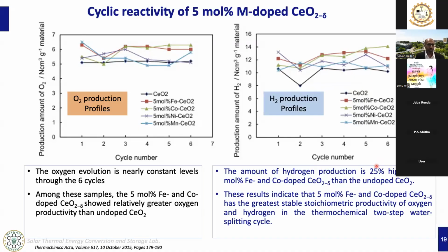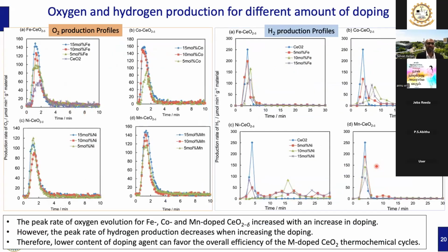This slide shows the overall oxygen and hydrogen production of all samples for different amounts of doping. This slide shows all samples, like 5 mole percentage of iron, 10 mole percentage of iron, 15 mole percentage of iron, and other materials also, from 5 to 15 mole percentage of doping. From all results, as you can see, the peak rate of oxygen evolution for iron, cobalt, and manganese doped cerium oxide increased with increase in doping. However, the peak rate of hydrogen production decreases with increasing doping. And lower content of a doping agent can favor the overall efficiency of the metal doped cerium oxide thermochemical cycles. That also you can notice.